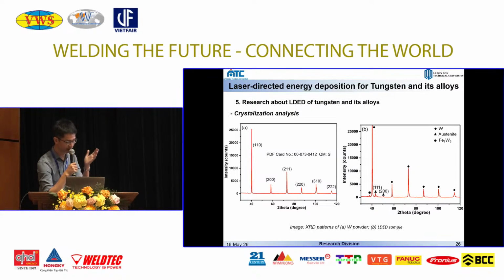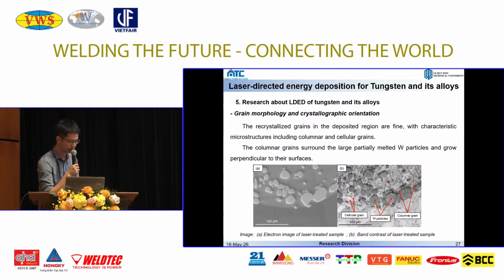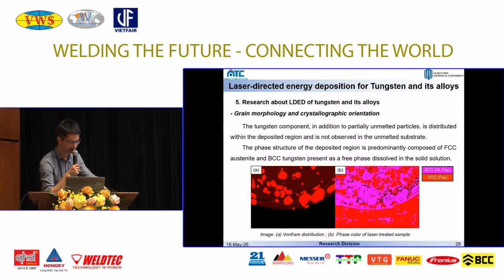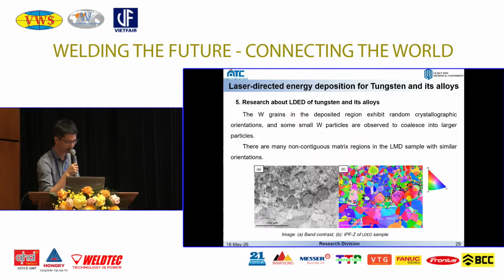For a deeper understanding of the crystallization of the sample, we did XRD analysis here. On the left side is the XRD analysis for only tungsten powder, and on the right side is for the LDED sample. On the LDED sample, some tungsten intermetallic structures appear in the peaks of the XRD. To investigate the grain morphology and the crystallographic orientation, we did EBSD characterization, and we can also see phase changes due to the LDED process. This is a very fancy image of the band contrast and IPF of the LDED sample.